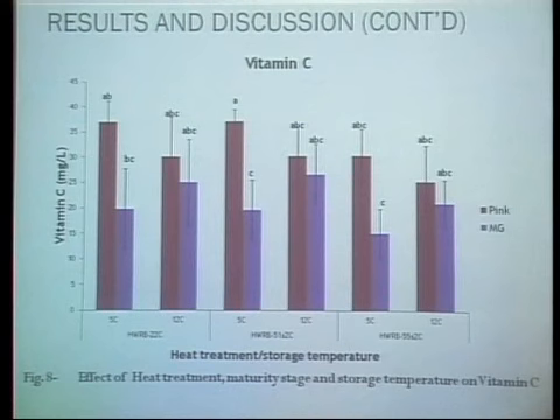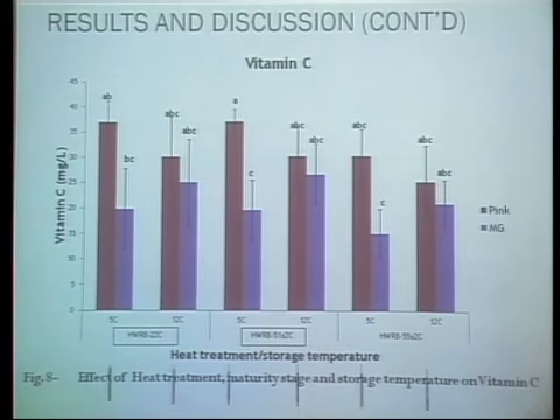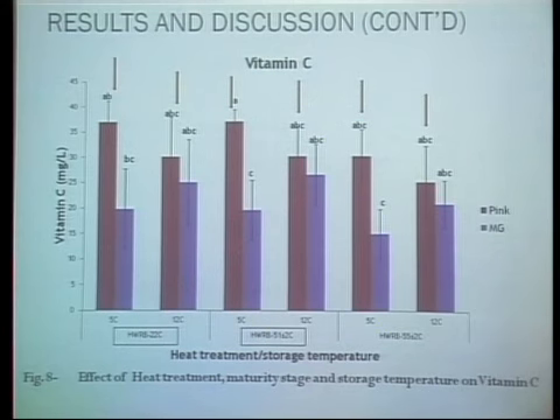And if we look at the vitamin C also, the heat treatment didn't have any significant effect on the vitamin C. The maturity stage had a significant effect on the vitamin C. By the storage temperature, we didn't see any significant effect. So you can see in the graph that this heat treatment improved the vitamin C at 5. And vitamin C was also improved at 5 for the control. So we can see here that the pink fruits had a higher vitamin C as compared to the matured green.